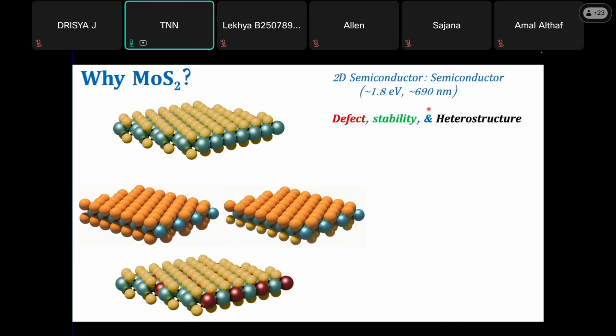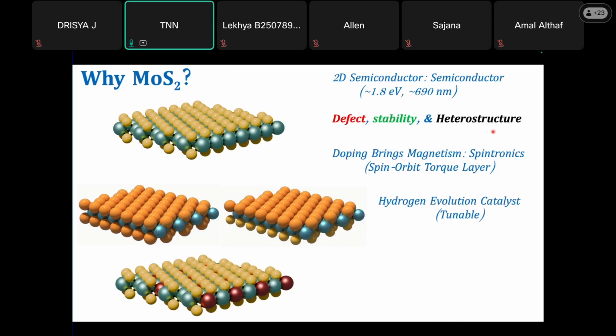Sorry, less than 1 nanometer. And the semiconductor band gap is around 1.8 electron volt. It's quite stable. It can form heterostructures. By doping, we found that it can bring room temperature magnetism. It is acting like a good catalyst, as I told you.